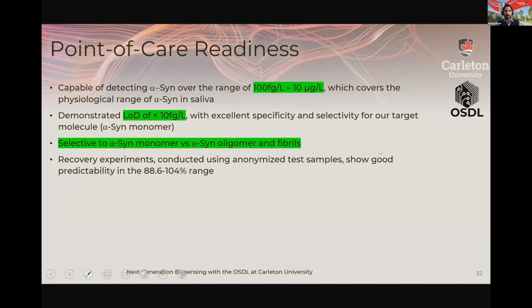We can say that because we have shown detection range, which covers physiological range of alpha-syn in saliva, CSF. We have predictably demonstrated a low limit of detection, which is better than immunoassays. We have shown selectivity in detecting monomer to the aggregate. Our recovery experiments have been impressive. Granted, we haven't done a lot of them, but the plan is to do a lot of these to establish this.